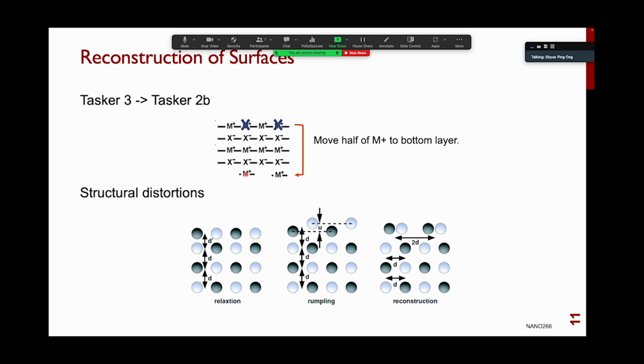You just move atoms from the top surface to the bottom surface or vice versa, which is equivalent. And essentially what you have now is a positive surface at the top and a positive surface at the bottom. The overall cell is still charge neutral, and your surfaces are of course no longer stoichiometric, but at the very least you don't have a polarization of your surface, okay? All right.